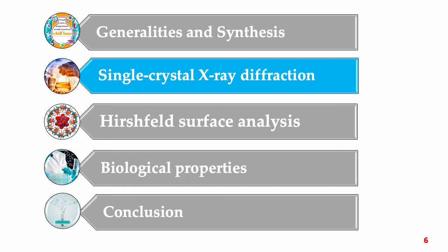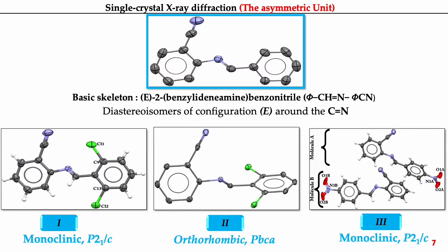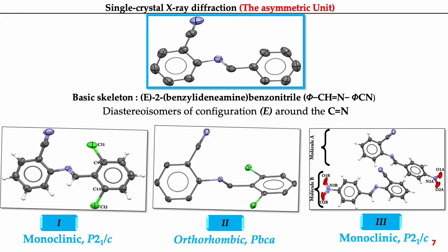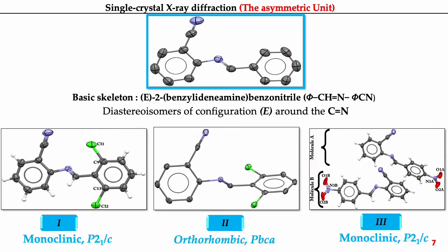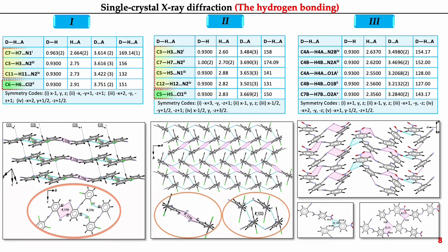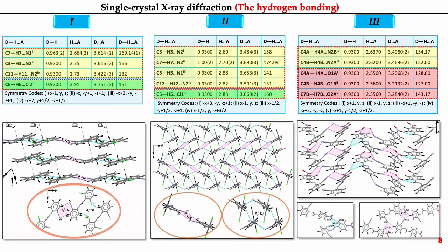Now, I will present the single crystal X-ray study of our new Schiff bases. The crystal structures of our Schiff bases have the same skeleton, 2-benzylideneamino benzonitrile, with different substituents, 2,6-dichloro for compounds 1 and 2, and 4-nitro for compound 3. In the crystal of 1 and 2, the molecules are linked by C-H...N and C-H...Cl hydrogen bonds. However, the molecules of compound 3 are linked by C-H...N and C-H...O hydrogen bonds. As we can see in these figures, each structure arises as 2-dimensional layers.